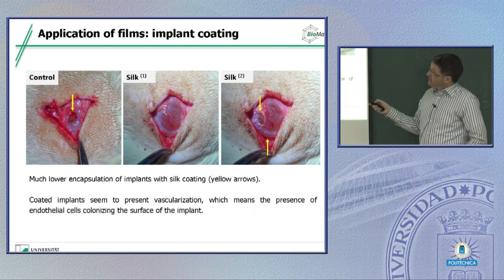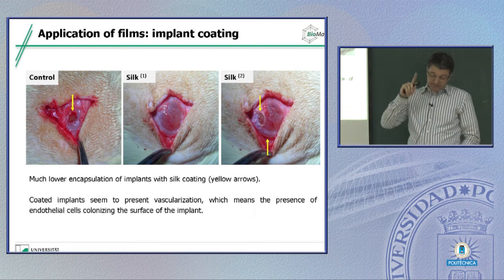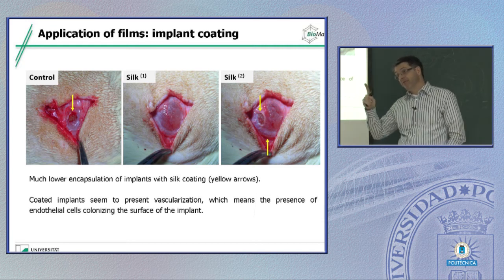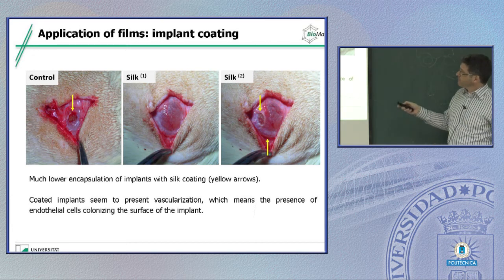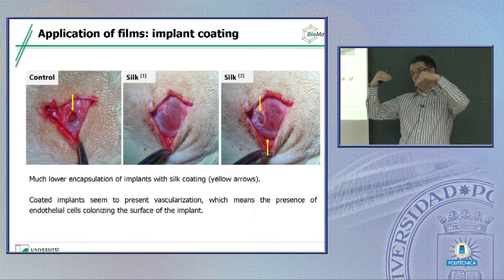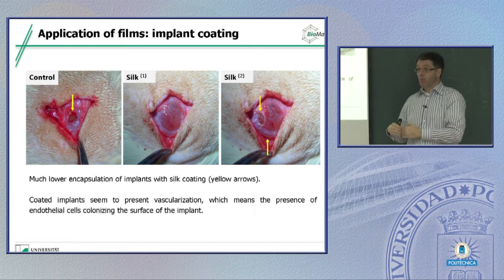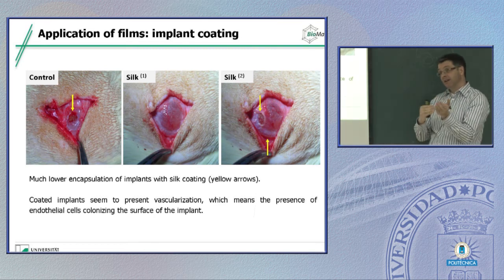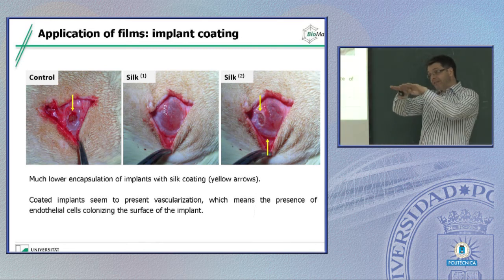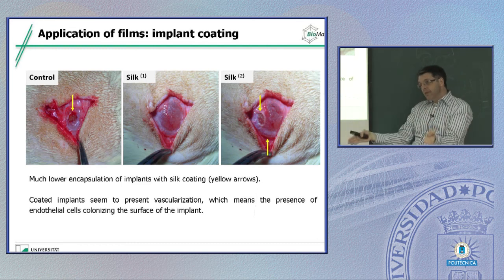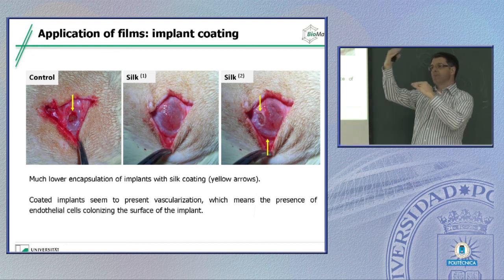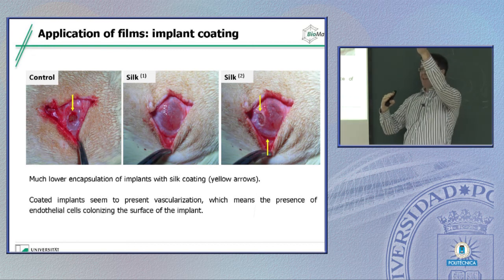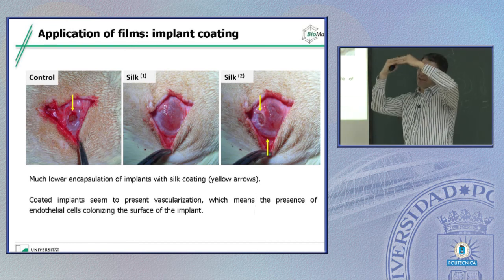So what we found with having these silk coatings, and again, remember, silk is amphiphilic, the silicone surface is quite hydrophobic. So what happens here is that the silk, again, like with the capsules, brings all the hydrophobic surfaces towards the silicone. And this somewhat interacts also with the unbound silicone oil. And actually, you make kind of an oil layer underneath the silk film, but the oil cannot pass the silk membrane now, because the silk membrane on the other side is hydrophilic, right? So you have sort of a repulsion.